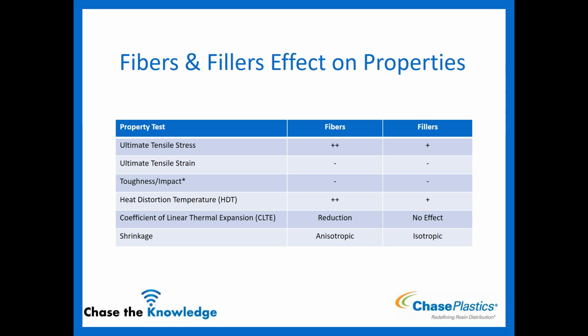Your heat distortion temperature or DTUL, deflection temperature under load, if you're used to the old verbiage, is going to increase with your fibers, and it increases a little bit with your fillers. It's more drastic with your fibers. Then your coefficient of linear thermal expansion, again, these are properties we're going to talk about if you're not familiar with them. You'll see a little bit of a reduction with fiber usage, and then not much of an effect for fillers because of the way that they're shaped, and we'll get into that as well. And then for shrinkage, we're looking at an anisotropic shrinkage. So it's going to be different in different directions. Again, we'll talk about that more, but you're going to see that with your fiber reinforcement. And then with your fillers, it's more isotropic or more uniform in each direction.